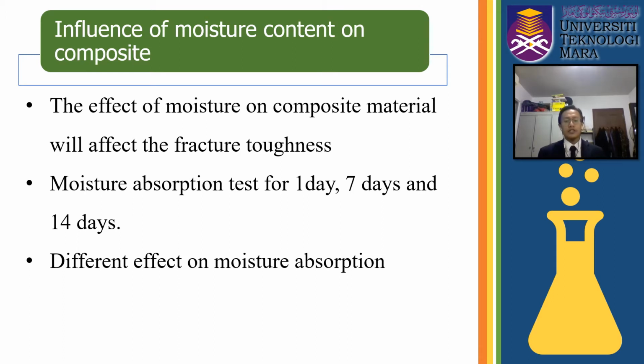It is important to study the effect of moisture on composite material. Moisture absorption test is a suitable test to investigate the effect of the moisture on the composite. In this project, the specimen was submerged into distilled water at room temperature for 1 day, 7 days, and 14 days. The effect of the composite with different moisture content can characterize the interlaminar fracture toughness as the ratio and moisture content level. The aspect that can be known is that the same type of composite will have a different effect on moisture absorption.